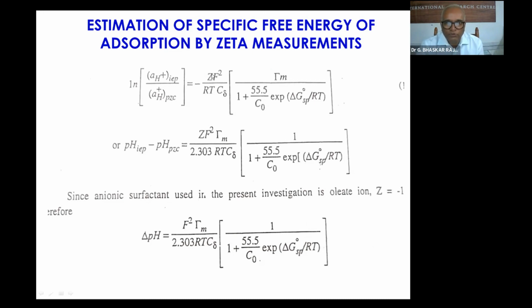For example, oleic acid is RCOOH, so the valency is 1. This is the Faraday constant, this is the gas constant, temperature, and this one is the dielectric constant of the medium, so that the delta G specific adsorption you can find out. This gamma m is the adsorption density of oleic acid on sillimanite.